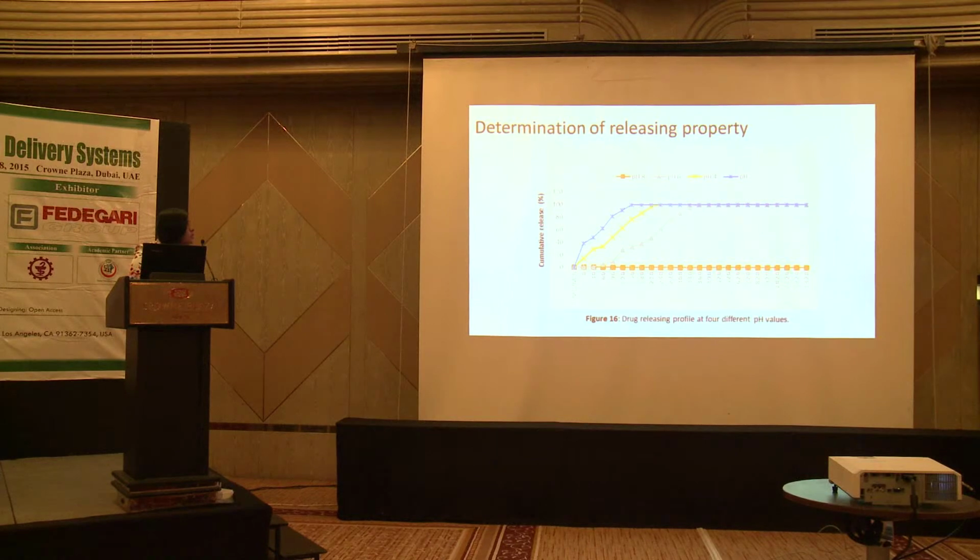Next, the determination of release property. At four different pHs, we determined the release property of the encapsulated product. We determined the amount of copper released using atomic absorption spectroscopy. At pH 8, for 24 hours, no release was observed. But within 4 hours, 100% release was observed at pH 6, 4, and 2.